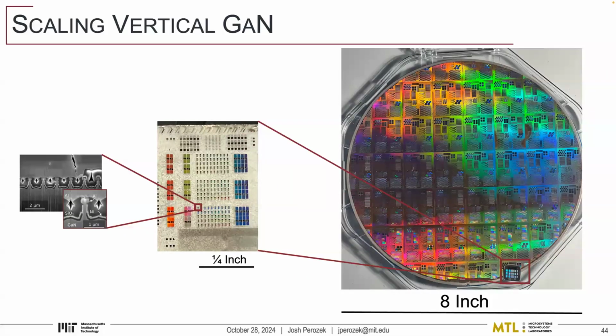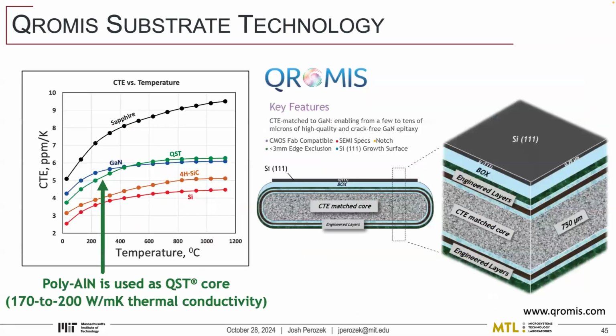This becomes a lot more challenging. There's a lot more uniformity that you have to take into consideration. One of the biggest problems with doing this is just where do you even buy 8-inch gallium nitride wafers? What we've always seen is gallium nitride grown on silicon. And the problem with that is when you grow gallium nitride on silicon, you're growing these things at like over 1,000 degrees Celsius. It's very hot. And if you look on this plot, looking at the coefficient of thermal expansion for these materials, you'll see that as it cools from those high temperatures down to room temperature, the gallium nitride is going to shrink a lot more than the silicon. And if you're above a certain thickness, that gallium nitride just cracks.